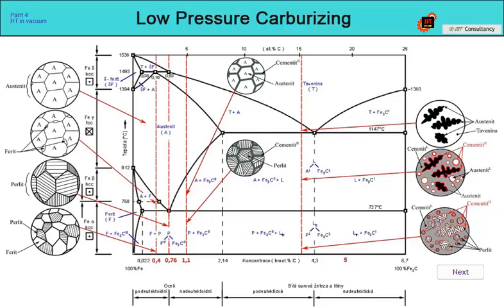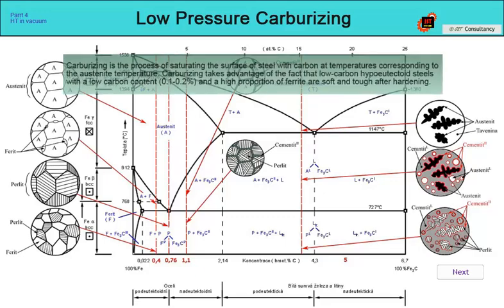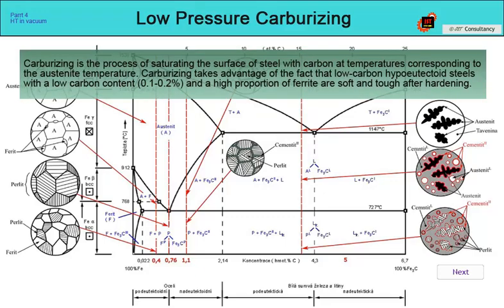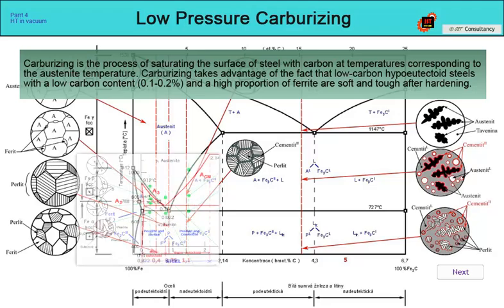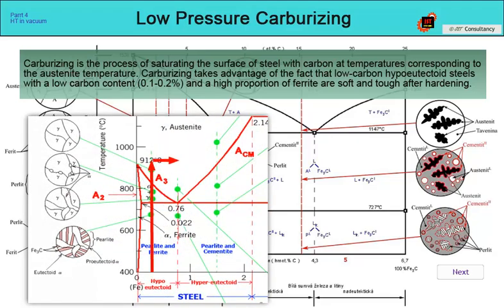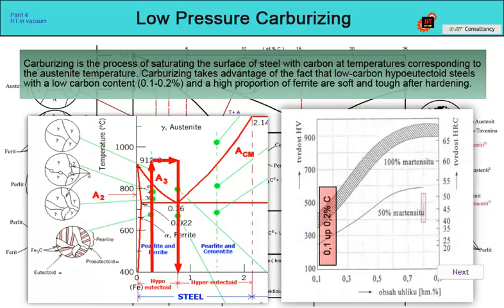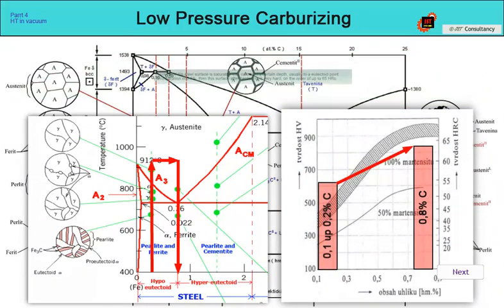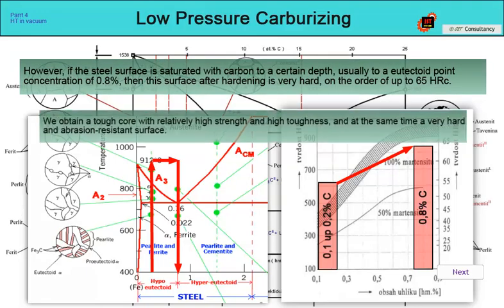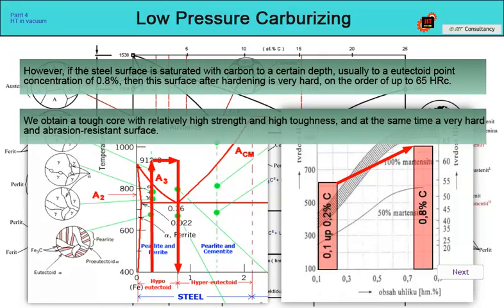To understand this better, we need to go back to the iron cementite diagram. Carburizing is the process of saturating a surface with carbon at temperatures corresponding to austenite. In case of carburizing, it is used that sub-eutectoid steels with a low carbon content of 0.1 to 0.2% and a high portion of ferrite are soft and tough after quenching. However, if the surface of the steel is saturated to a certain depth with carbon, usually to a concentration of eutectoid point of 0.8%, then this surface after quenching is very hard, up to 65 Rockwell.